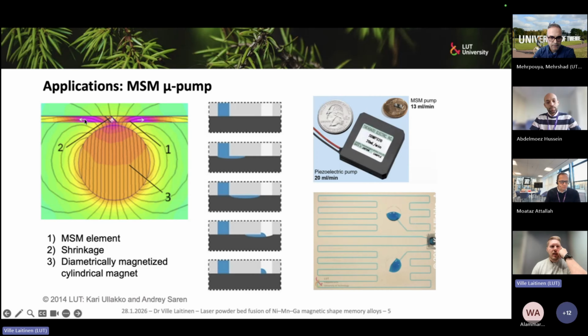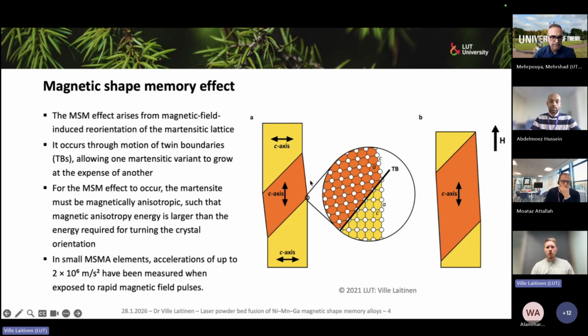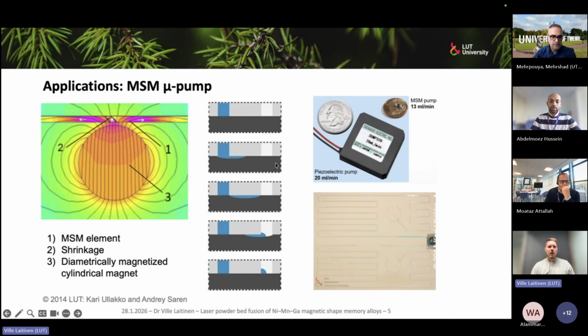Basically, in the sections where the magnetic field is distributed along the length of this stick, the C axis of the crystallographic lattice tries to orient in that direction. In the sections where it's at a 90-degree angle, the C axis tries to go in that direction. So what happens in the element is that it generates this kind of uneven twinning. Because of this physical kink between different elements, these kinks accumulate in a way that generates undulation. Now when we rotate this magnet, this field distribution will change. So by rotation, this undulation will move along the surface of the single crystal.